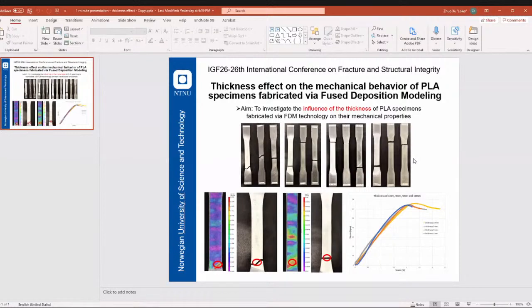No, in this case, I include all of them in the results. One phenomenon I observed is that most of them actually break near the gauge region, but I carefully checked, and it's all within the gauge region. One reason is the fabrication process. Instead of printing starting from the edge of the specimen, each layer starts somewhere near the gauge region. So this spot may have some defects from the fabrication, which is why the majority tend to break here.